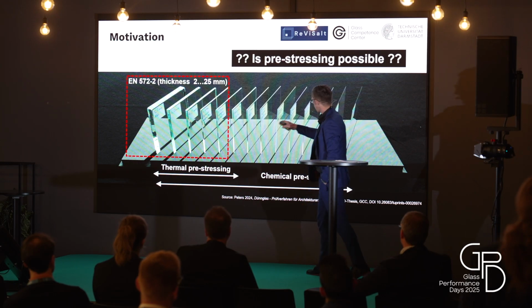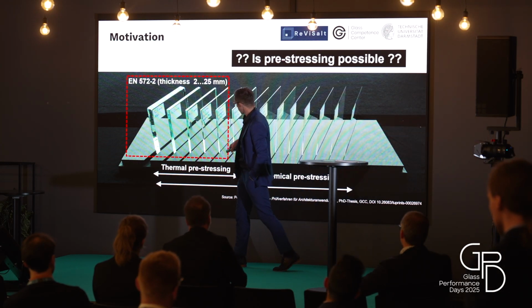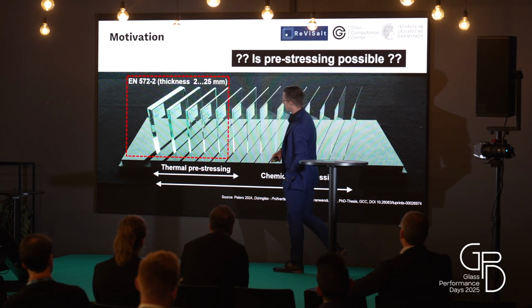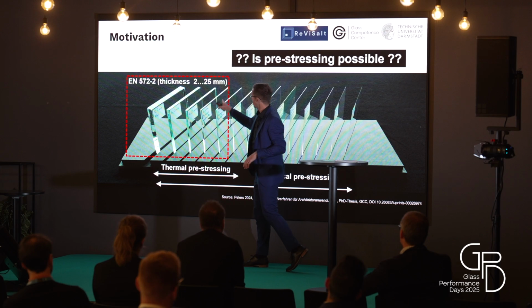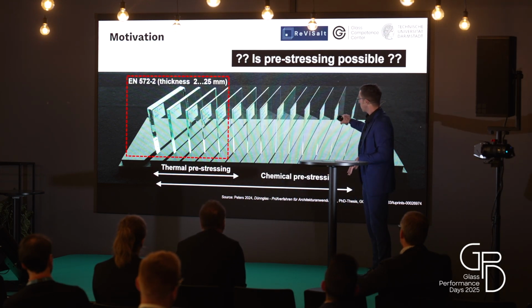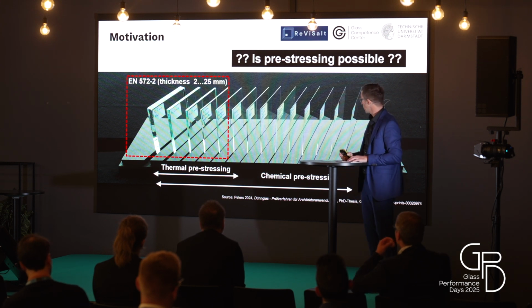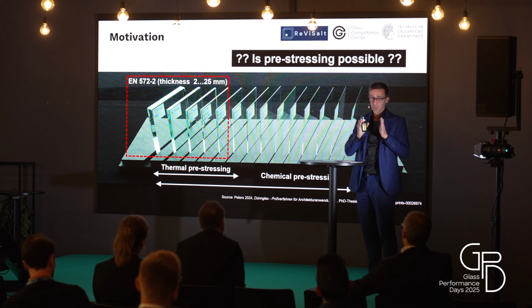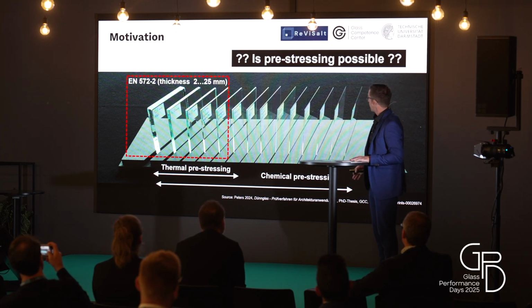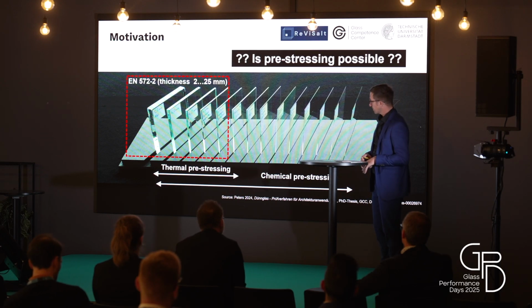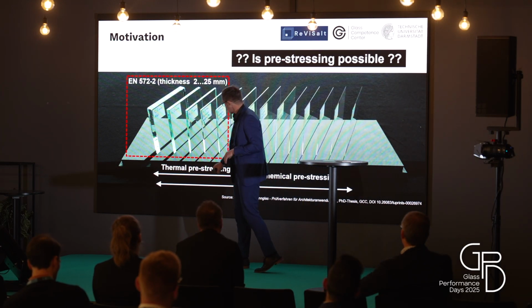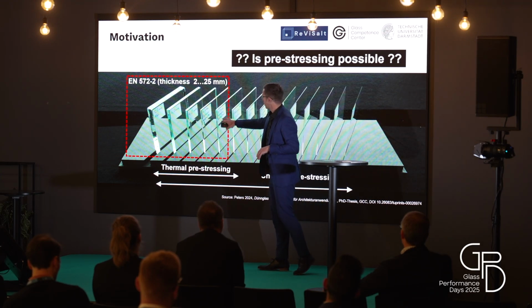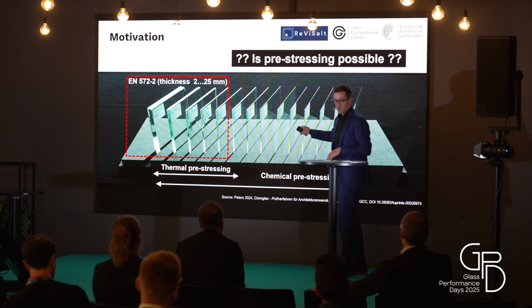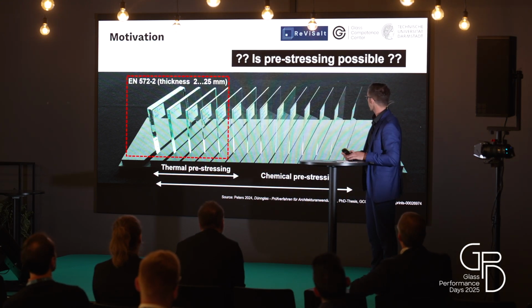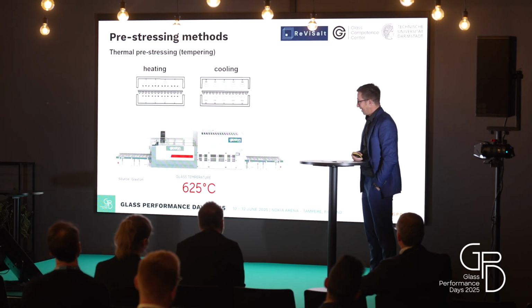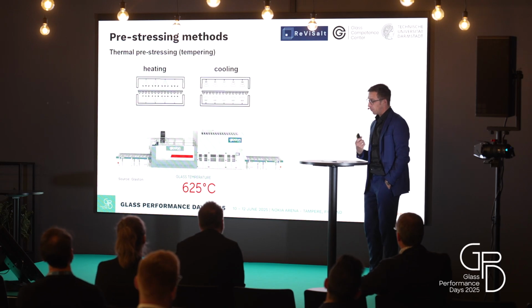Here you can see different pieces of glass, different thicknesses, different materials. It's not only soda lime glass. This is the soda lime glass standard in Europe, and for the building sector it's only allowed to use this thickness at the moment. But we know also from the display industry, and from Corning and also Schott, they can produce really thin glass, up to 30 microns, I would say. But can we do a pre-stressing of this? For architectural glass, it is possible to do the pre-stressing up to 2 millimeters, more or less. This was not possible. We can do the chemical tempering, yes, but this is expensive.